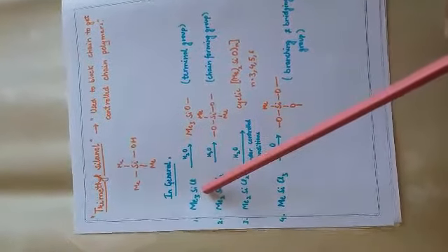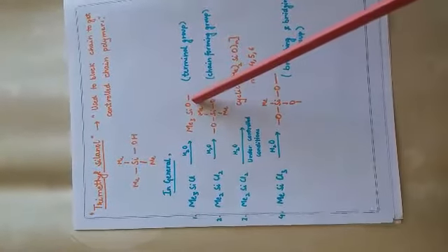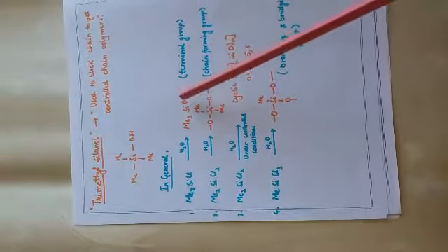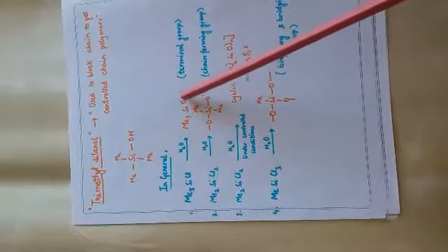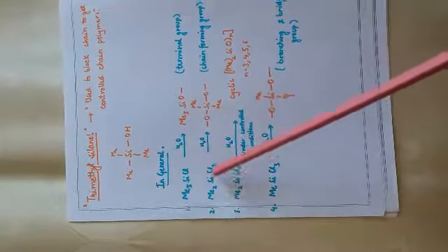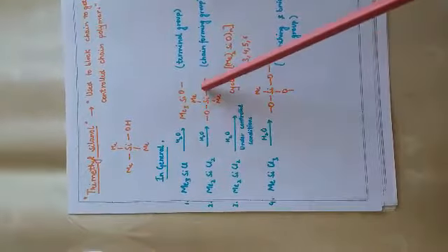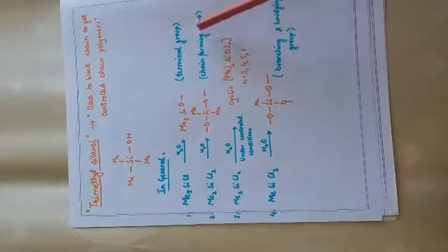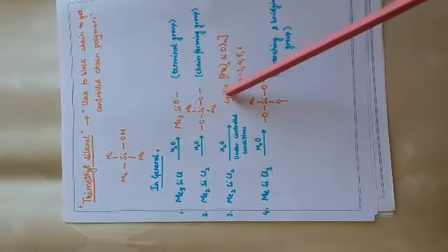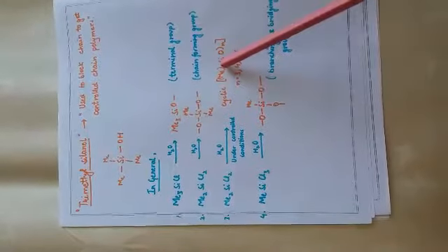length. So in general, the trimethylchlorosilane, when hydrolyzed, forms trimethylsilanol, and it is a terminal group, which we have seen here, which acts as a blocking subunit. Terminal because on the terminal side it has one oxygen group, so it can extend towards a single terminal. If we have dimethyldichlorosilane, then on its hydrolysis we get hydroxyl groups attached on 2 sides, and it can extend the chain length across both sides. So it is acting as a chain forming group. Similarly, if it is hydrolyzed in a controlled condition, then it will act as a cyclic chain forming group. It will form a cyclic, ring-like structure.